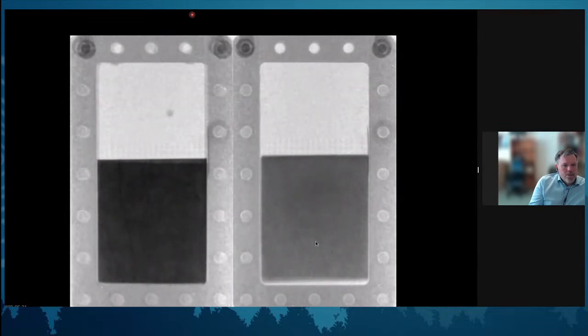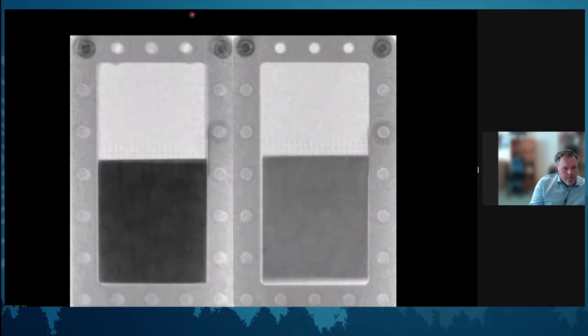And when this has dried, the right one, we still have not dried the left one that had twice the amount of water. Now we can see that it starts to dry eventually at the edges.